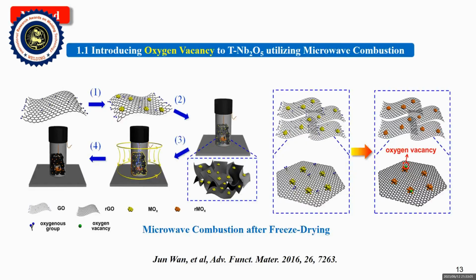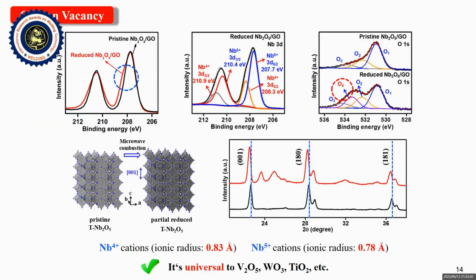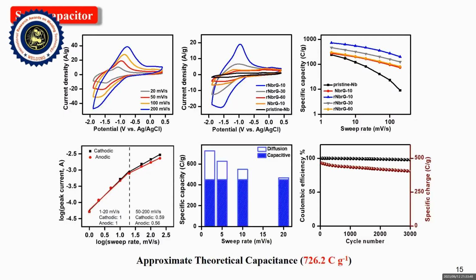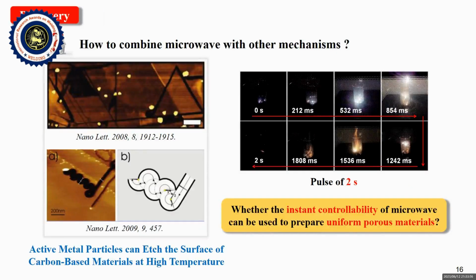GO and niobium pentoxide were mixed together by ultrasound. Then the oxygen vacancy can be introduced by microwave combustion after freeze drying. Because of the reducibility of carbon and GO, the XPS of the oxygen element after microwave reaction shows an obvious peak of oxygen defect. These phenomena are universal to other oxides, such as vanadium oxide, tungsten oxides, and so on. This sample could show approximate theoretical capacitance.